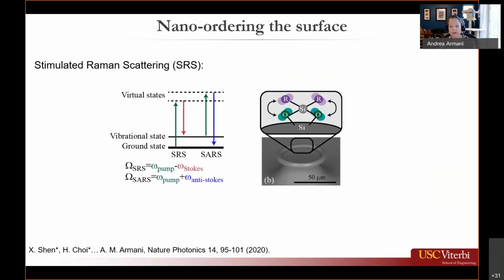So what we wanted to do was to see if we could modify the surface, so create a structured surface that would allow us to improve the Raman gain of the system by creating a nanostructure or a nanocrystal on the surface, and therefore increase the Raman gain, but still maintain that very high Q factor. And in doing both of those, we would be able to decrease the threshold as well as increase the efficiency of the system. So those previous devices typically had efficiencies of 4 to 6%, so very low efficiency devices. Additionally, by increasing the efficiency, we should be able to get anti-Stokes. So not only get emission at a higher wavelength from the pump, but also at a lower wavelength from the pump.